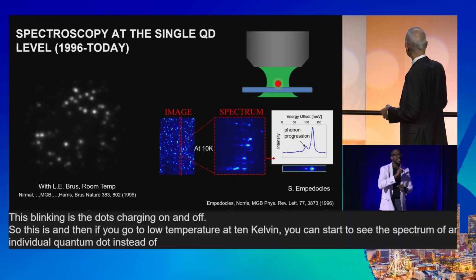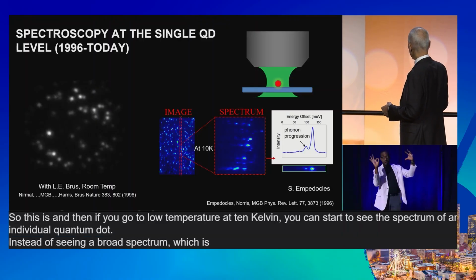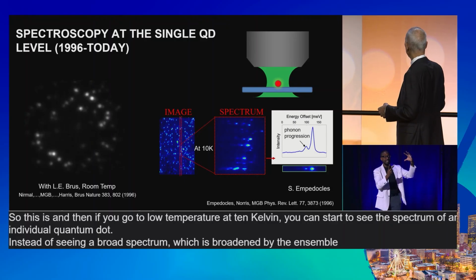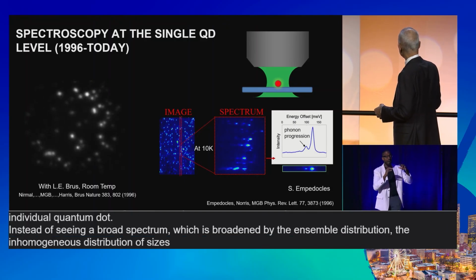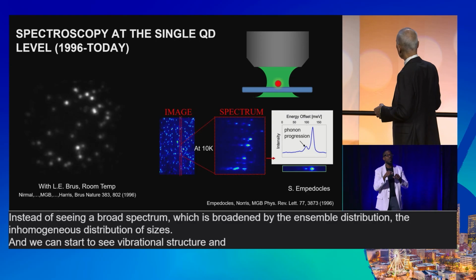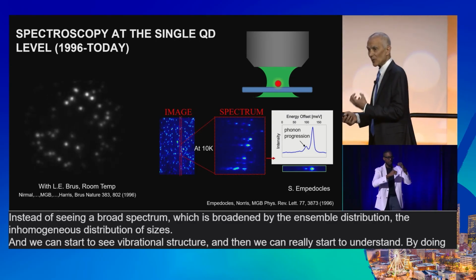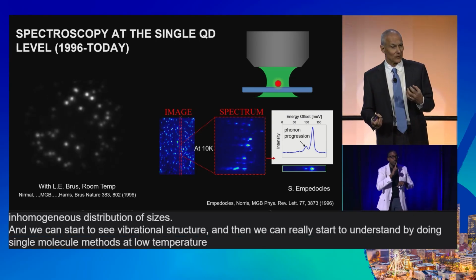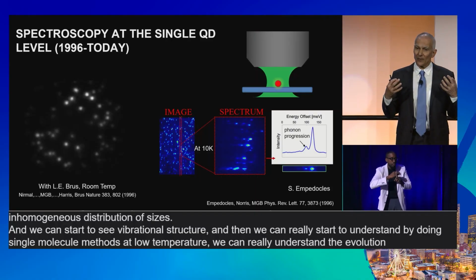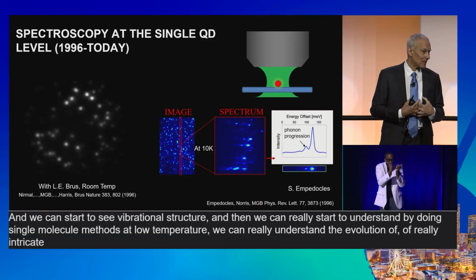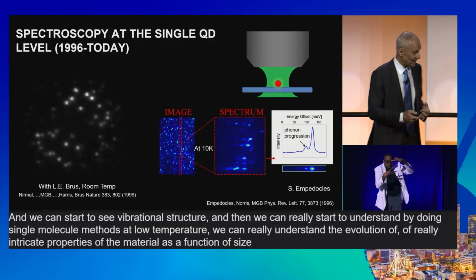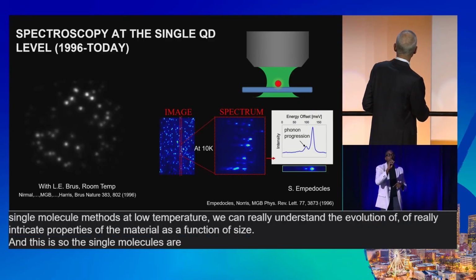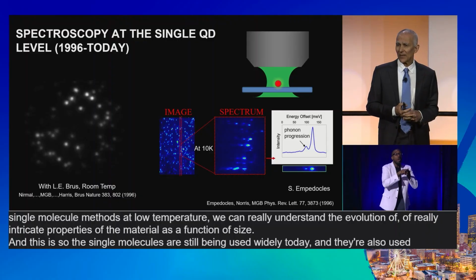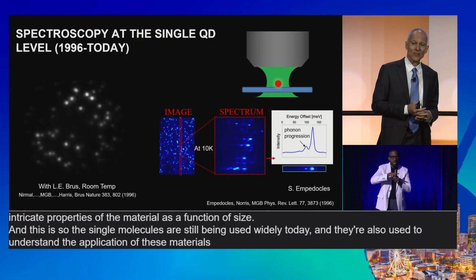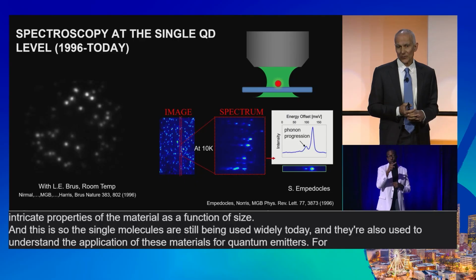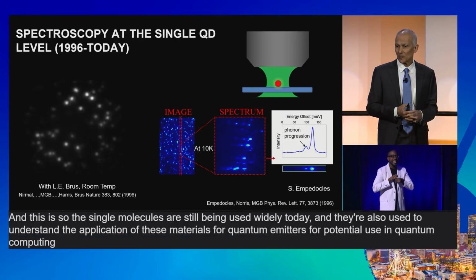Instead of seeing a broad spectrum, which is broadened by the ensemble distribution, the inhomogeneous distribution of sizes, we can start to see vibrational structure. And by doing single molecule methods at low temperature, we can really understand the evolution of really intricate properties of the material as a function of size. And so these single molecule methods are still being used widely today, and they're also used to understand the application of these materials as quantum emitters for potential use in quantum computing or quantum cryptography, for instance.